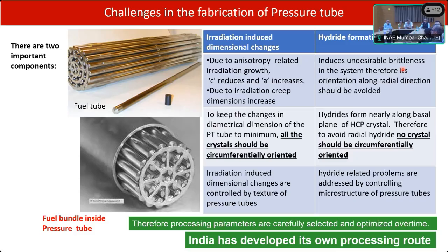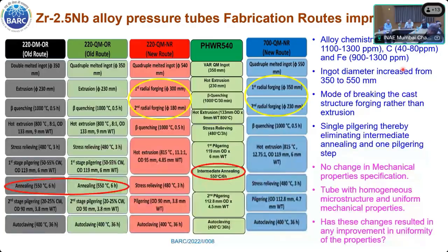Now the problem is that the requirements from the hydrogen, or hydride, point of view and from the irradiation point of view don't really match. They are rather contradictory to each other. So you have to find an optimum solution and work from there. That is why we had a lot of problems in the beginning in making our zirconium alloys, and a lot of struggle took place. What we were trying to mimic was the Canadian material. This is where the problem started.